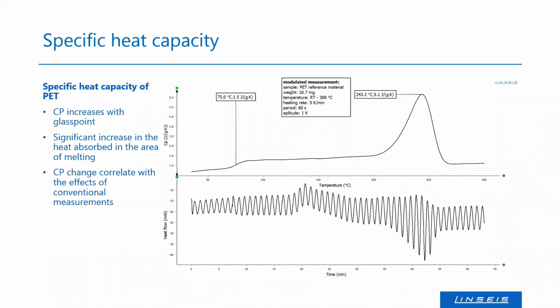And of course, this correlates with the amplitude of our raw signal below. During the glass transition, the amplitude gets higher. At the recrystallization, we can see in the raw signal that the amplitude is constant, and for this reason, we cannot see it on the CP signal. And then during the melt, of course, there's much heat needed to heat the sample up. So here, the amplitudes are extremely high, and later, it's lower again. And also on the CP signal, we can see here the CP of the liquid is lower than the solid before.